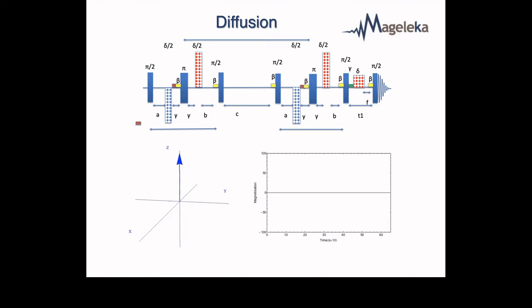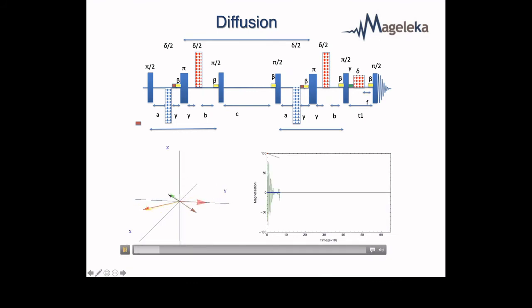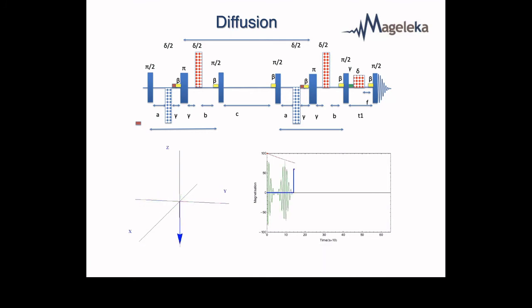They sound like loud clicks in your ear, and in fact, if you listen to our machine, it clicks away quite happily. And in between here, we do a rather complicated NMR experiment. But at the end, we have a signal that we can measure. And this is a graphics of this experiment. We switch on the field gradient, and instantly the signal seems to disappear. But it's now diffusing through space. So if we like, we took a snapshot of where the molecules were. Then a little later, we take another snapshot, and we compare those 2 snapshots. And from those 2 pictures, we can work out how each of the molecules has moved.